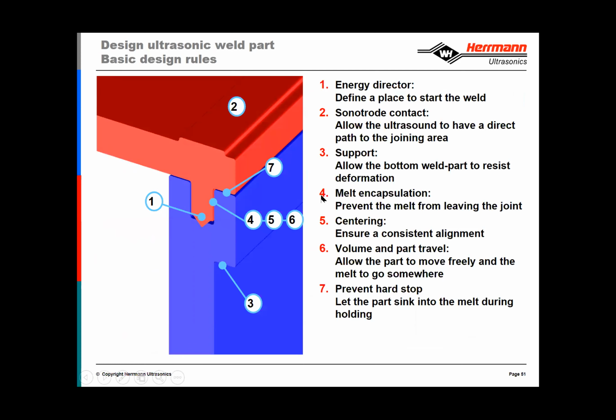Number 4, melt encapsulation. So again, calculating the volume of melt that's created by the energy director, that it stays contained within this tongue portion of the blue part. Number 5, centering. If you aren't able to fully encapsulate in this tongue and groove formation, if you only have a step joint, making sure that the parts stay centered, that they don't essentially fall off during the welding process is very important.